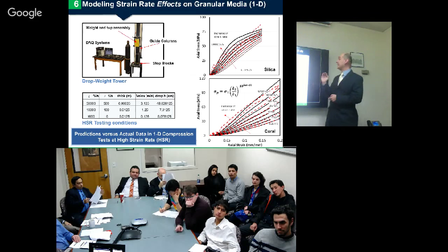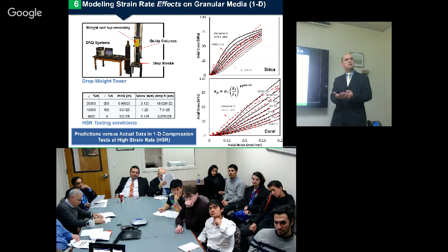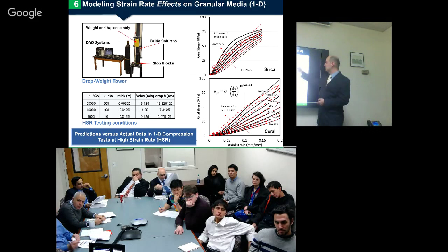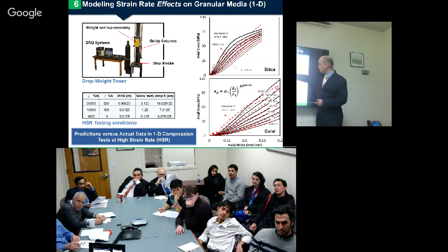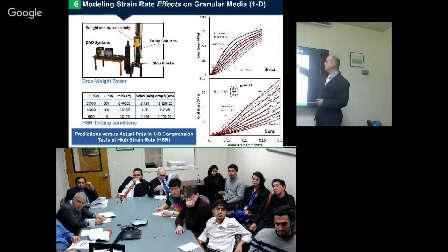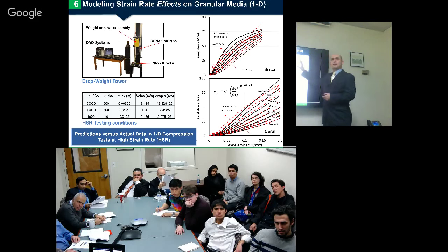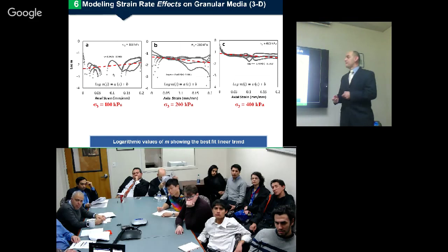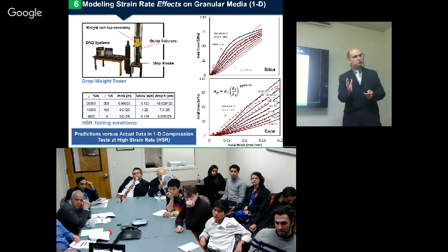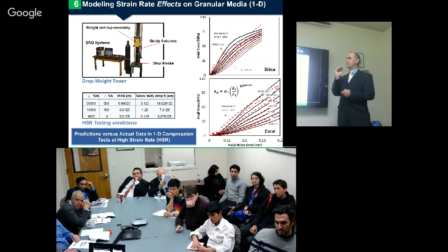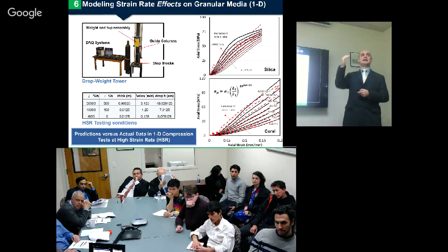So we can see the model provides very useful and good results for applications from quasi-static to low, intermediate strain rate. But when we go higher, especially in this material, I don't know if you are able to identify this curve. It doesn't even follow these two lines. It goes back, and it shouldn't do that if the model is applied at this strain rate. So in other words, the model is useful, but only when the strain rate regime is not very high.